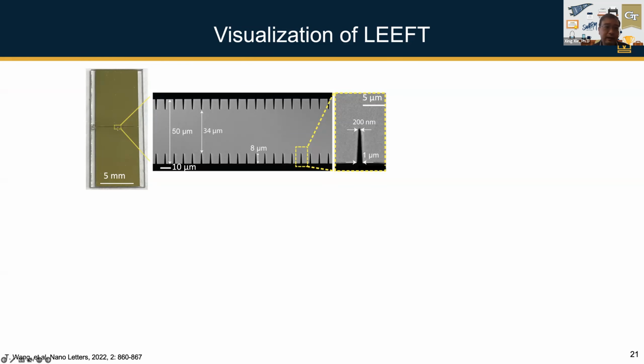And then if you zoom in on the gap here, you will have these nano wedge structures. The tip is about 200 nanometers, the bottom is about 1 micrometer. This is pretty much the smallest feature we can fabricate while still being able to see it very clearly under the optical microscope. We have tried to make smaller ones. In terms of fabrication, you can make much smaller ones, just like those in the real device we use, which are about 100 nanometers or even less in diameter.